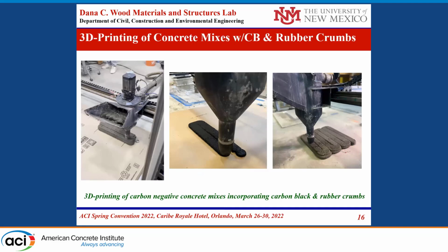Showing you the printing. This is two different types of mixes here. One with a low content of carbon black, and it also has some rubber crumb particles in it. The idea of using the rubber particles is to reduce the modulus of elasticity and to increase the fracture toughness. We also published about this before. Rubber particles can be between fine and large particles, usually in the same nominal maximum size and size distribution of the aggregate. And the other one, you can see it a little darker, includes about 20% carbon black in it, as a replacement of the aggregate.